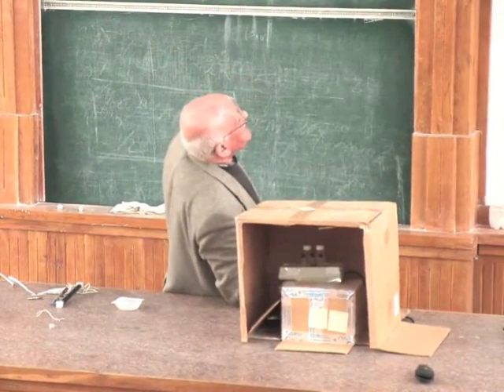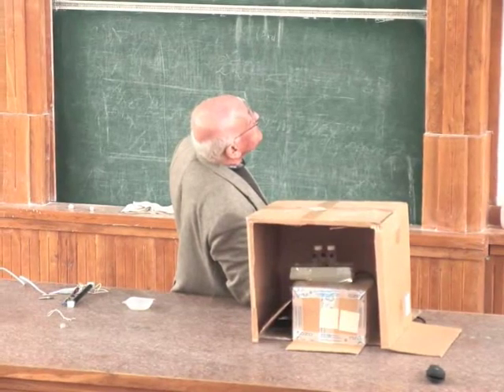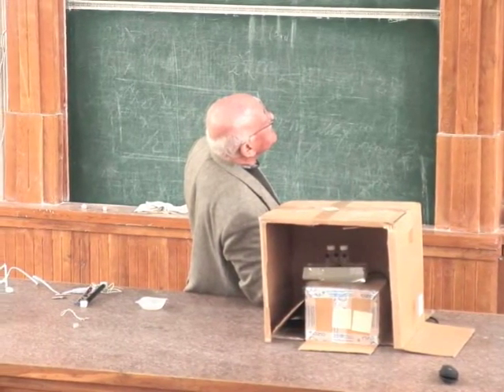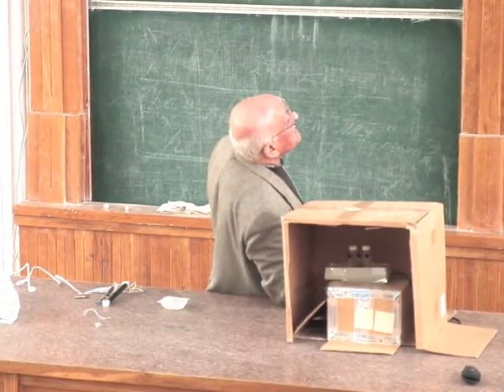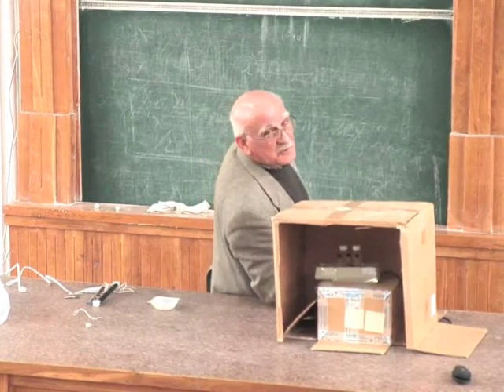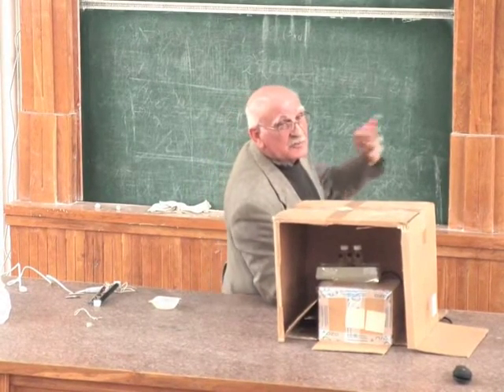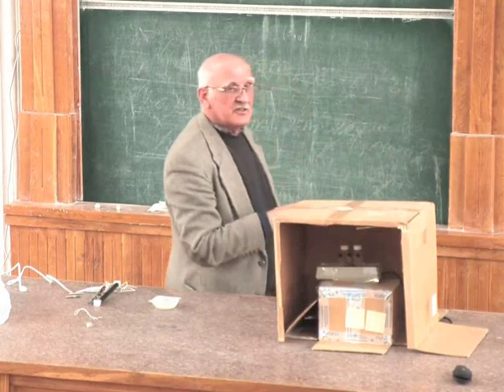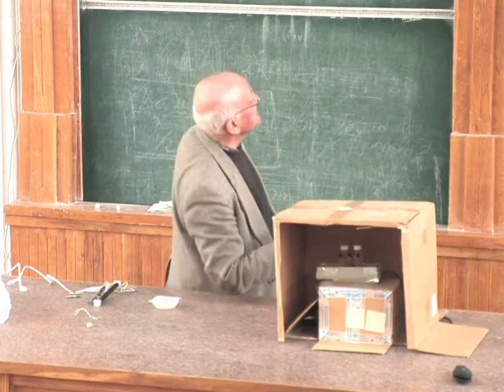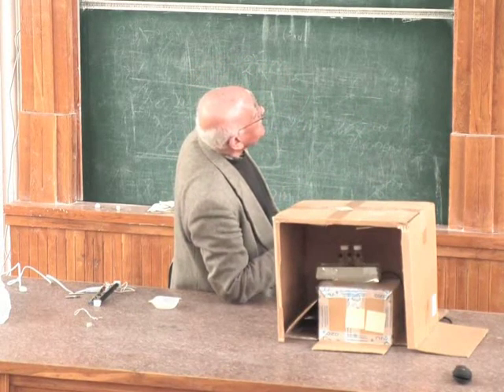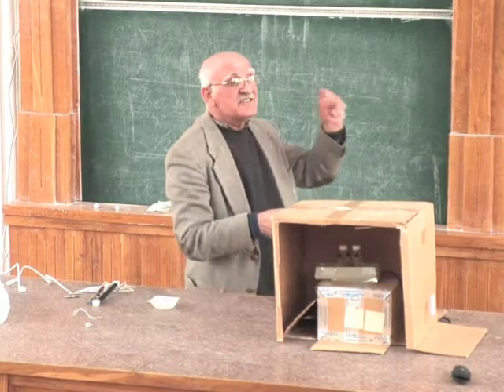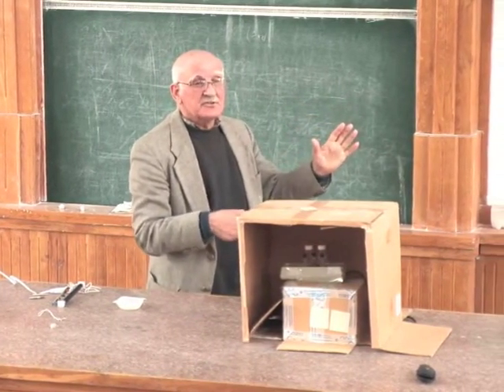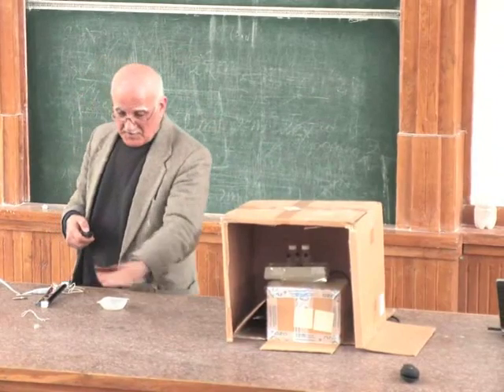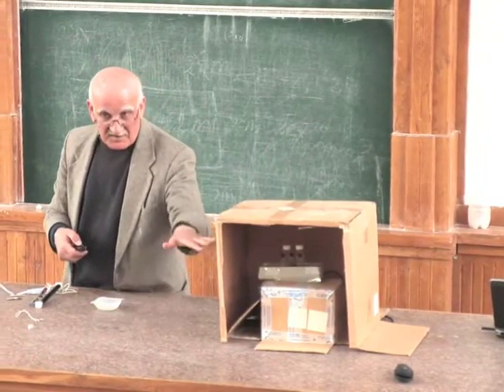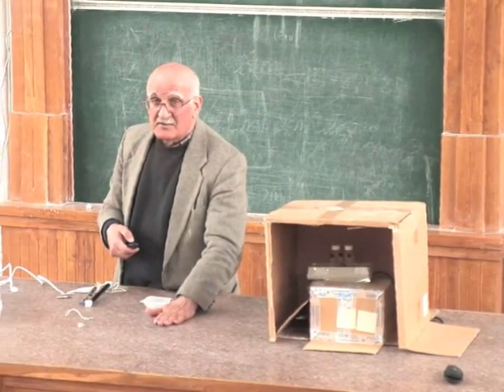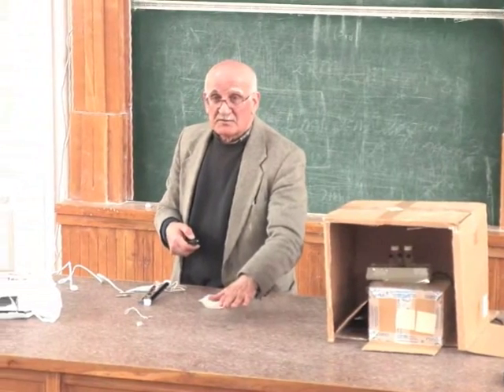Or electrically based. You could use electric deposition or electric spray. But that means you have to charge the nanoparticle, and there are easy ways of charging them in a liquid. I'll show you an example. Or because they are identical in size within each group, they self-assemble. You just put your substrate in the liquid inside this bottle, wait, they self-assemble, and you remove it.